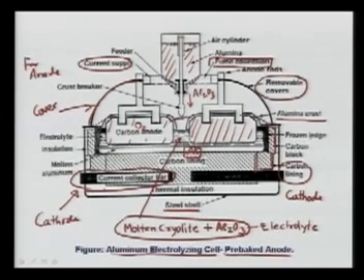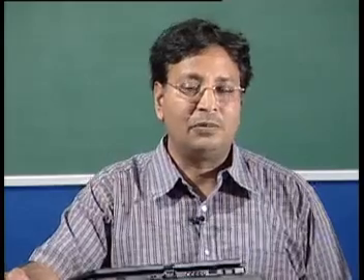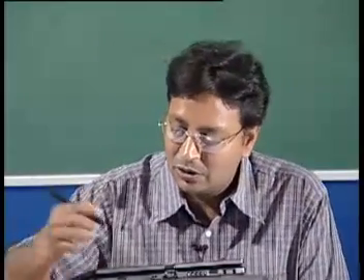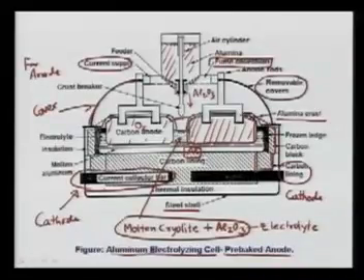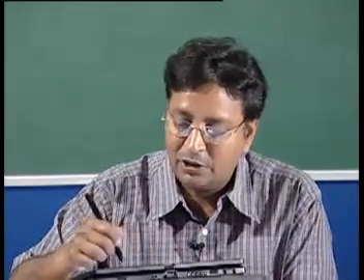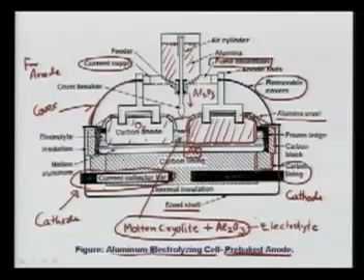The anode you see here is already pre-baked. It is in solid form. Something baked, as when you go to the bakery and find solid baked things like a biscuit, is not a paste. That's what is called already baked, so we call this pre-baked. Why do we need to say pre-baked? Because the system I'm defining to you right now has a pre-baked anode, but there are technologies where the anode need not be pre-baked, and we'll see those in a moment.